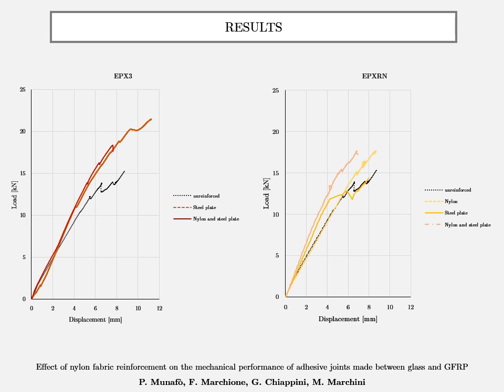The stiffness of the beam reinforced with nylon and steel plates applied with epoxy resin is significantly higher. The bonding with resin is more efficient with respect to the third structural adhesive. Finally, the nylon 6 fabric, in addition to the steel plates, increased the stiffness of the resulting structure by 29% with respect to the unreinforced beams.